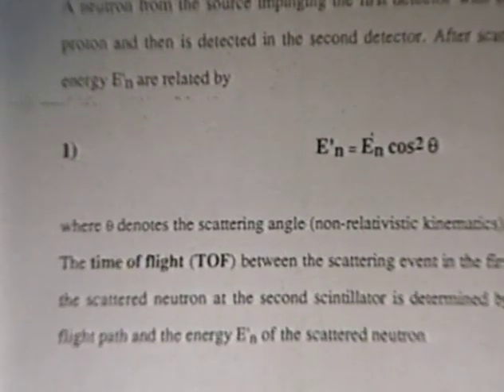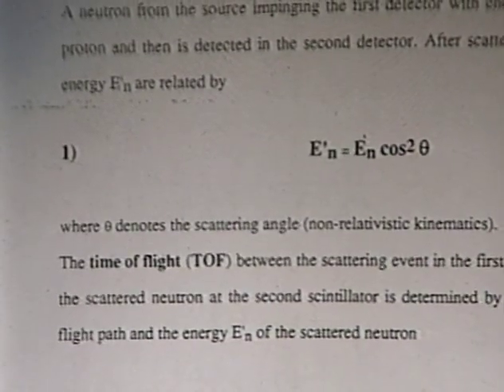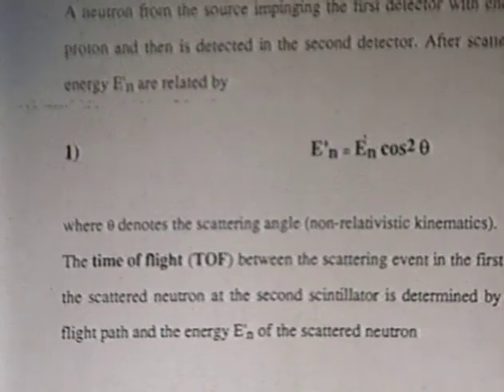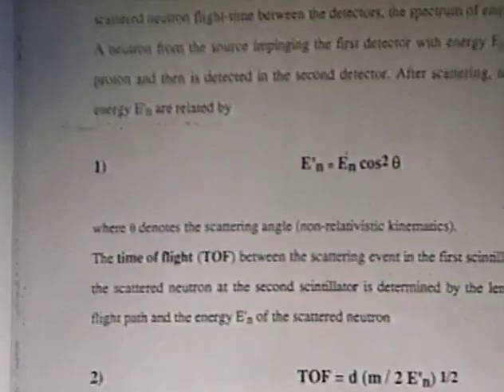I will give you some principles of the instrument. When a neutron with energy E0 impinges on the first detector, which we will call the scattering detector, the neutron will be scattered to the second detector with energy E1. And clearly there is a loss of energy which depends on the angle of scattering. The time of flight between the first and the second detector is given by the ratio of the distance of the flight path to the velocity, which we can obtain strictly from the energy E1.